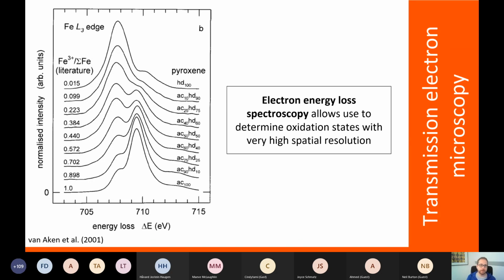Quickly to electron energy loss spectroscopy. So not only using the elastically scattered electrons, but also these inelastically scattered electrons. In earth sciences, for example, it is used a lot to determine the oxidation state at very high resolutions of, for example, here pyroxene, and you see a spectrum of the energy loss against the intensity. We're looking at, in this case, iron, and you see here how the spectrum changes from a dominant peak here to a more dominant peak on the other side. And this tells us something, and can be quantitatively expressed, about how much iron 2+ to iron 3+ is in our pyroxene. So we have a very powerful technique to, for example, look at oxidation states at very high resolution.